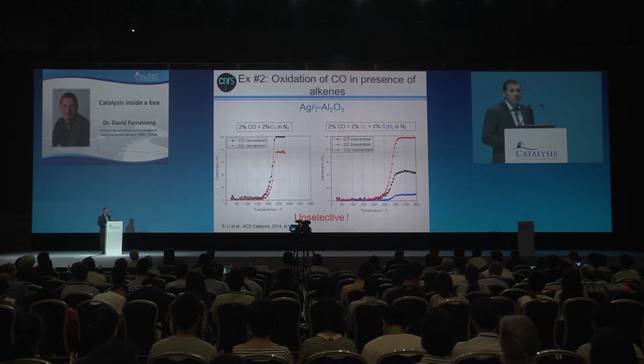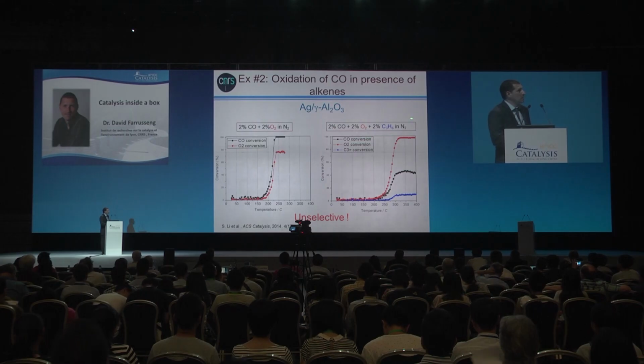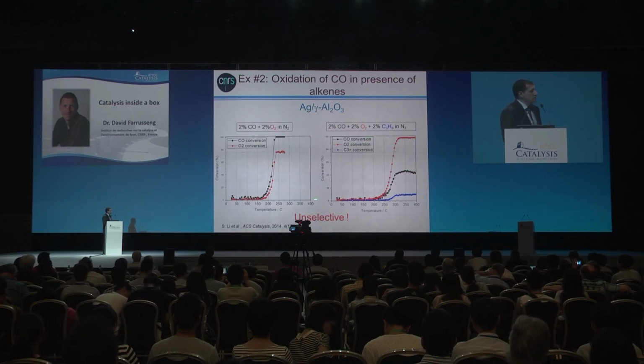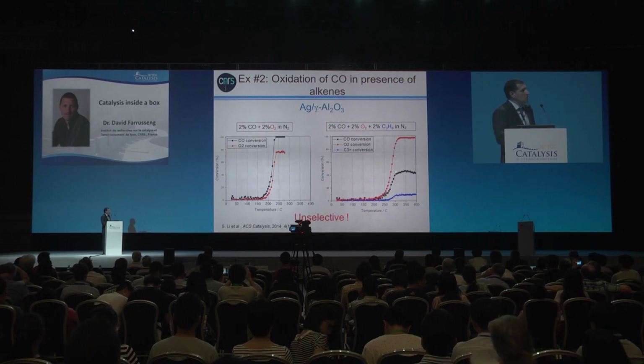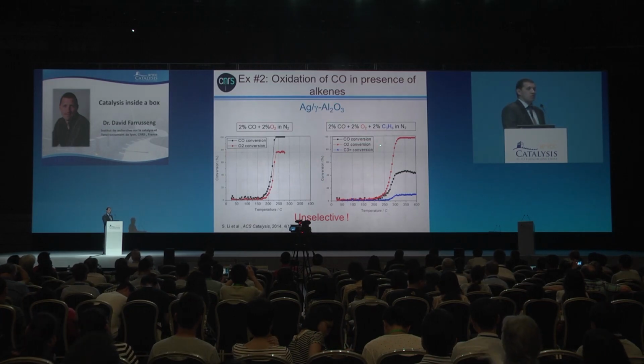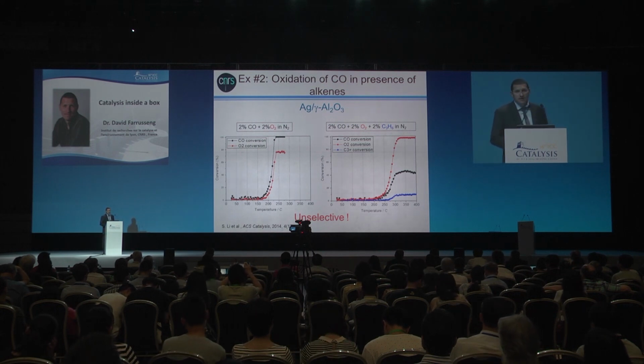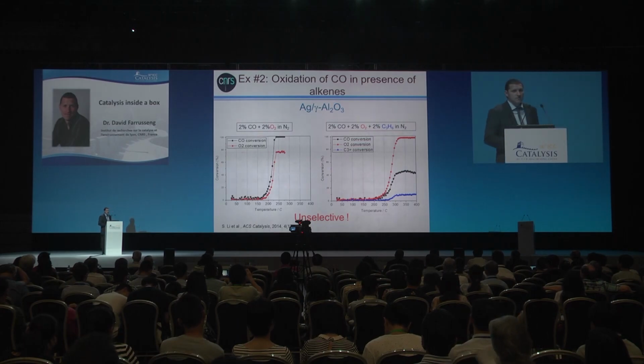Then we have another picture when we add propylene. You can see that in this case, the CO conversion levels off at 40%, and you wanted to have it at 100%, and instead you start to burn propylene. So it's not what you want. It's a very unselective catalyst.